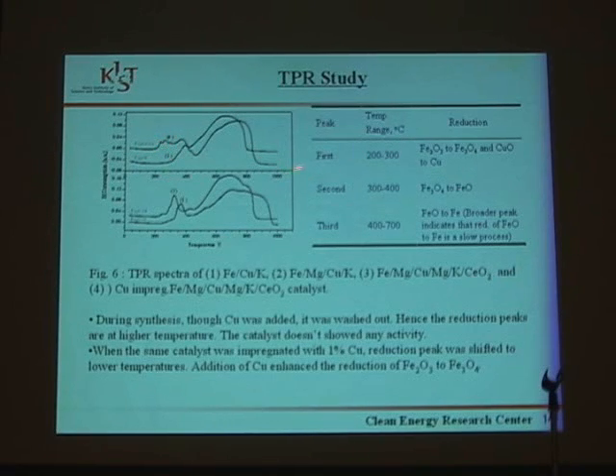So the first peak around 200 to 300 shows Fe2O3 to Fe3O4 reduction. Then the second peak, 300 to 400, is due to Fe3O4 to FeO. And the third one, this wider peak, is due to FeO to Fe, and the peak is wider because it takes a long time, it is a slow process. That is, reduction of FeO to Fe is a slow process, and hence we are getting a broad peak.